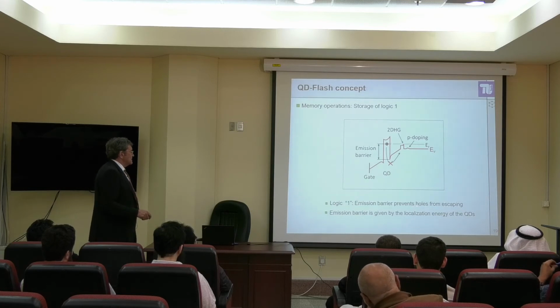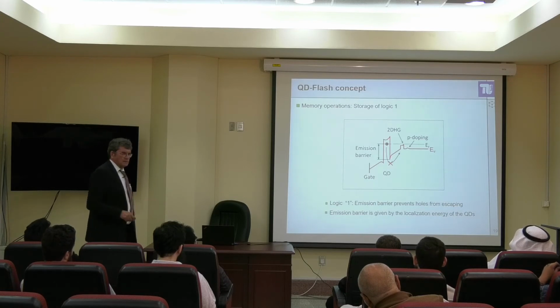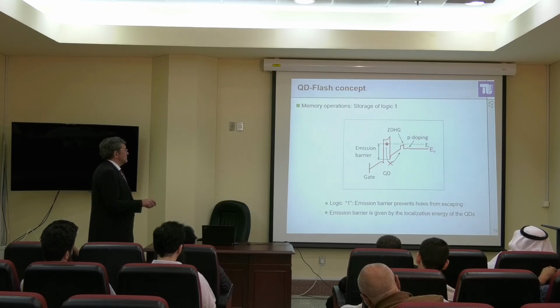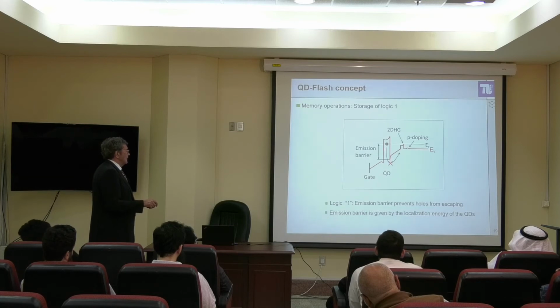The emission barrier prevents holes from escaping. That is the emission barrier here. And the emission barrier must be high, so that holes are not escaping. That is given by the localization energy of the quantum dot, that means the difference between this point here and this corner here. And if they can escape, they would go here. But they should not.